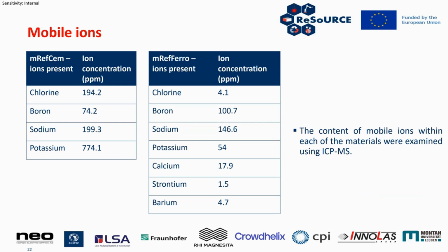We also performed some leach testing on these materials to see if there's any mobile ions present. We can see that there are some mobile ions, and these can be explained by the processes that these materials have gone through. So for instance, with the mRefCem material, we see the potassium and the chlorine that can be expected from the cement production industry.